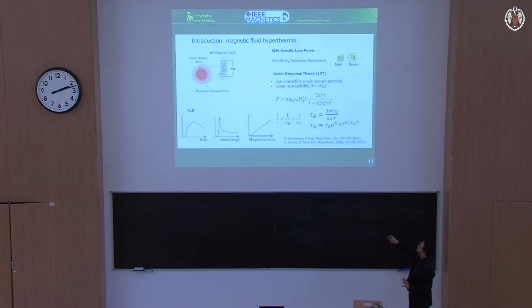So to increase the power dissipation, one simple strategy is to come up with materials with large magnetization. That's one way to increase the SAR. There is some size dependence, and it's very critical because it turns out that if the particles are too small, or if they are too big, they're not going to work. There is a sweet spot in this community. We know that the particle size has to be close to the single domain to multi-domain transition. Okay? It should not be really superparamagnetic. I'll explain to you why.